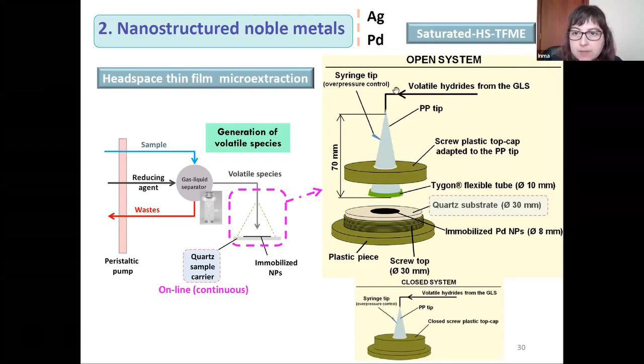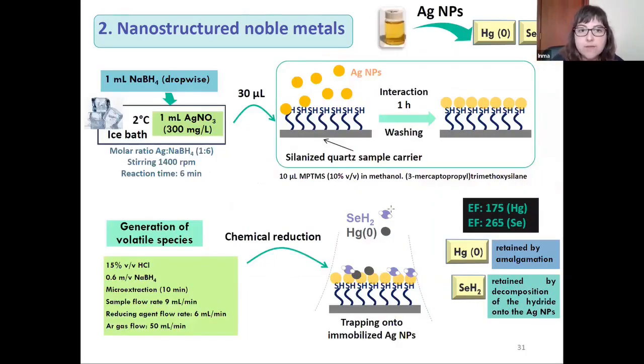Here we see how the volatile hydrides or mercury vapor arrive into this conical part, which is a polypropylene tip of a micropipette. And when it is closed, we see that there are no losses of these gases, and these vapors are trapped onto these palladium or silver nanoparticles. It depends on the work. In the first work, we have silver nanoparticles that were prepared by chemical reduction using sodium borohydride, that was added dropwise to a silver nitrate solution. Then these nanoparticles were added to a quartz sample carrier previously silanized using a silane compound. After interaction during 1 hour, this film was washed, allowing only to have the nanoparticles attached to this silane.